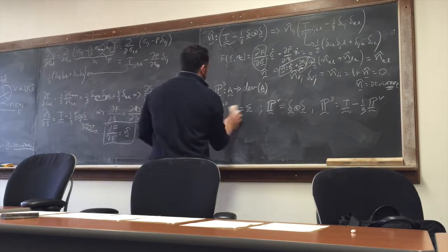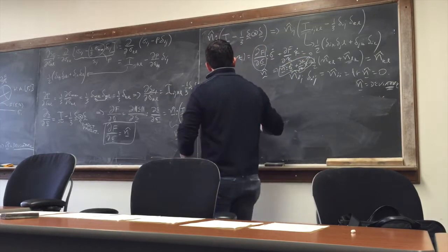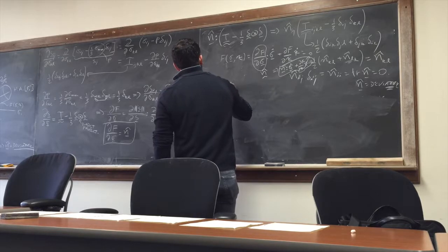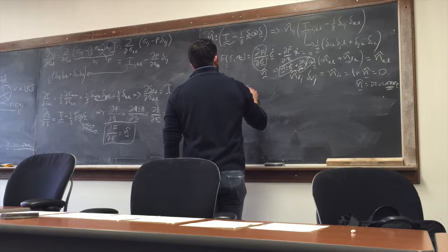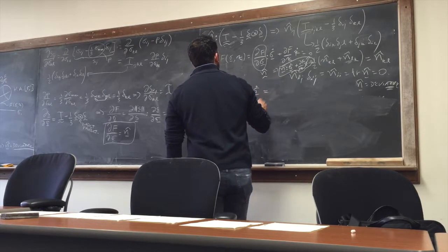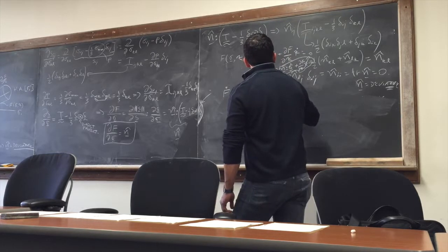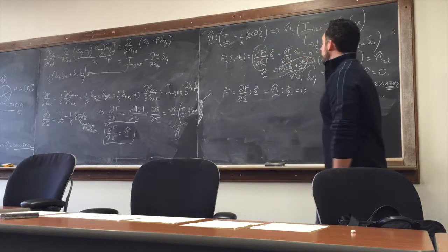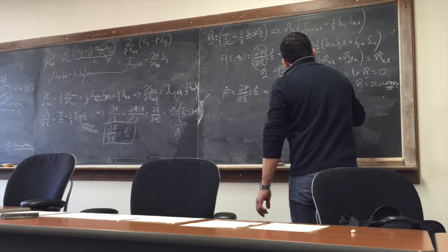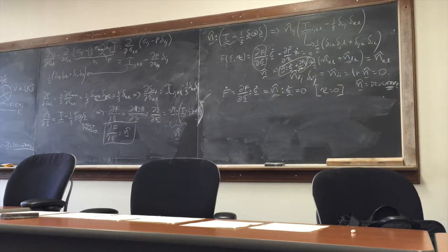reevaluating again what we started looking for, which is our F dot, our consistency condition, which is df d sigma double contracted with sigma dot. Now we know, right, that this is n hat double contracted with sigma dot, and that has to be equal to 0. Again, in the case when kappa dot equals 0, so in the perfect plasticity case. So what does that mean?